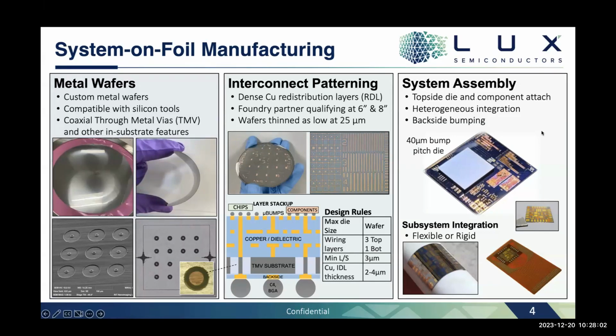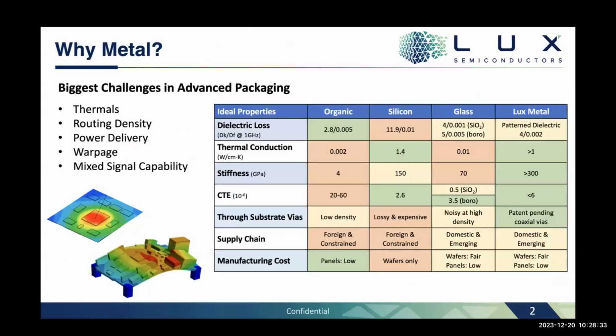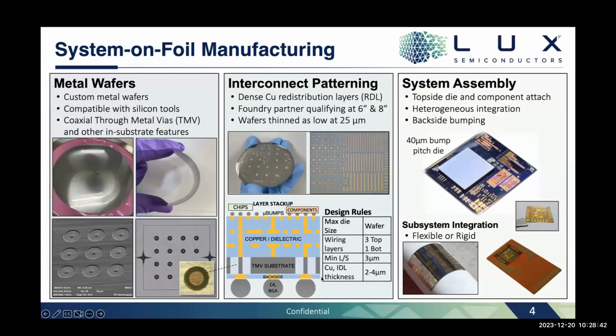Wait, how do you escape the challenge of the CTE mismatch between the dielectric and the copper core? So this is actually not copper. It's a different metal. We don't publicly announce that, but we do share that with all of our customers, and it is low CTE. It is below 6 CTE. But also you need your dielectric to match that, right?